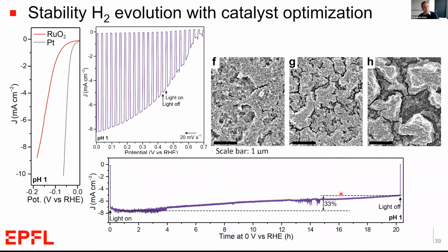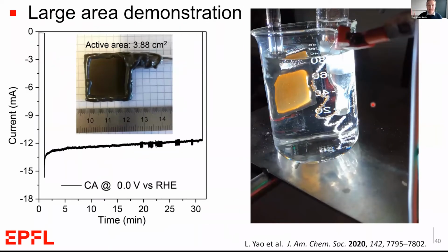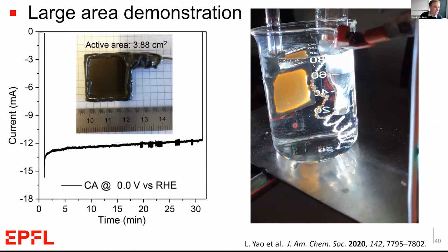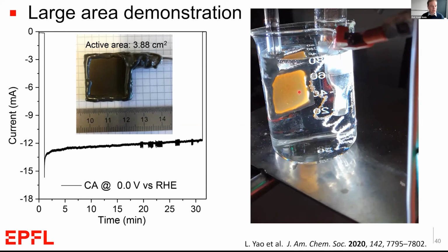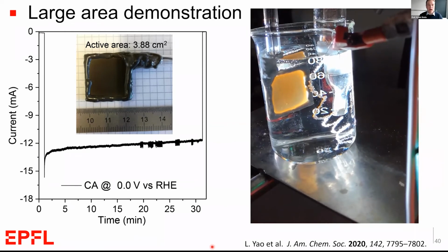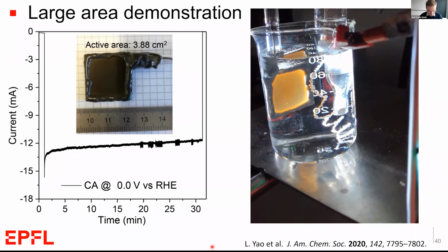Now, we think some of this decrease is due to the catalyst delaminating from the surface, as can be shown here with these SEM images. After 20 hours, we can see these cracks formed and some of the bare surface of the electrode revealed, meaning that the catalyst is falling off. So again, linking the catalyst better with the organic electrode will be quite important. But nevertheless, these are solution process-based materials. We can make them over large scale, and we can show this sort of stable hydrogen evolution now for on the order of at least one day.